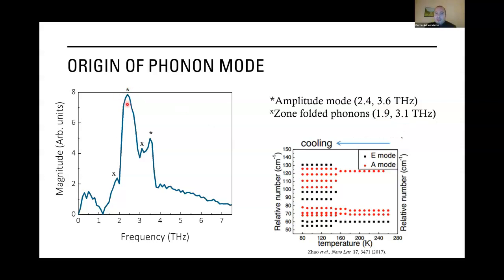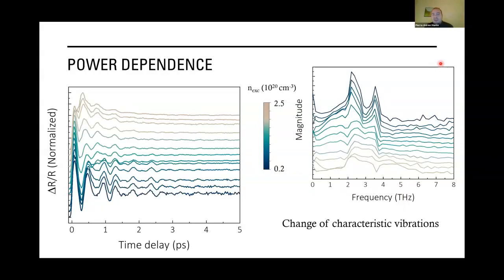And there's also this amplitude mode that is softening when we increase the temperature and getting closer to the phase transition, and that is representative of the charge density wave inside the material. So we performed experiments with increasing pump power, from this regime where we are at extremely low density of photo-excited electrons to really high power.